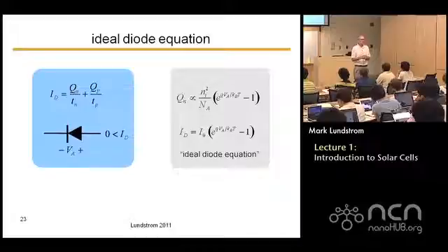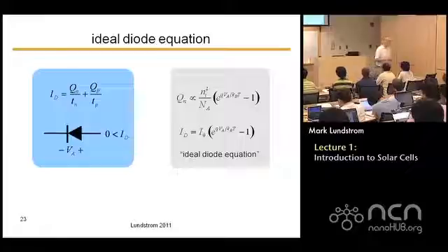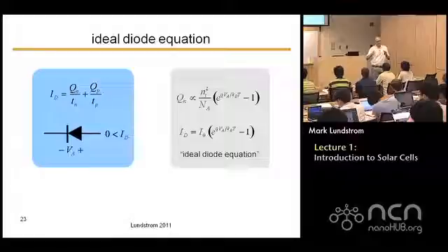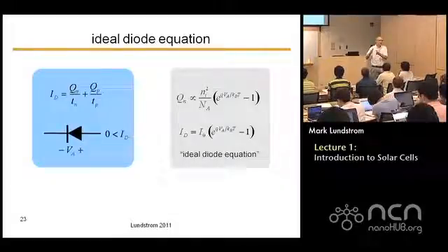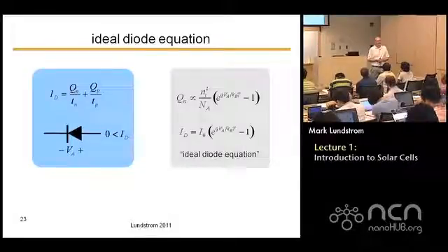Now in practice, we lose some by recombination, and I'm going to say a little more about that in my next lecture. In different types of cells, sometimes people design a cell where all of the generation comes in the junction region, where there's a strong electric field, which can take everything and quickly sweep it out to the right contact. There are other things you do to try to have minority carrier mirrors, so you make sure that the electrons don't diffuse to the contact and recombine there. You turn them around and have them diffuse towards the front. A lot of solar cell design is all about trying to maximize that collection efficiency.